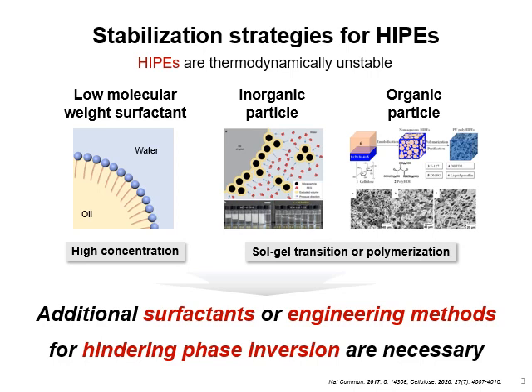Therefore, a large amount of surfactant is necessary for lowering the Gibbs free energy in the composition in which the dispersed phase exceeds the continuous phase. Armoring the dispersed phase with solid colloidal particles with sufficient adhesion to the interface, the so-called Pickering emulsion, enables the fabrication of stable HIPEs. However, in this case, the additional processing of solid particles via sintering or sol-gel reaction and polymerization is indispensable for making a colloidal interface more rigid, which again makes the release of the internal active phase out of such a robust colloidal shell challenging.